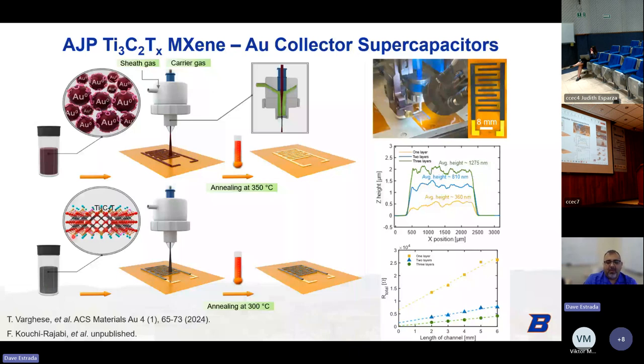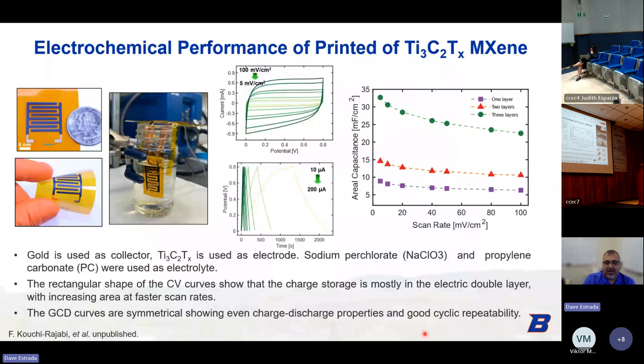And we can do this in a number of passes, a single pass, two passes or three passes, and get different amounts of MXene material on the current collectors, going from about 360 nanometers all the way up to 1.3 microns. So we have good control over the film thickness, and correspondingly the resistance decreases with the more MXenes that we deposit. So we can then take this IDE structure and dip it in the electrolyte to look at the supercapacitor performance. We did this both in our organic and ionic gel electrolytes.